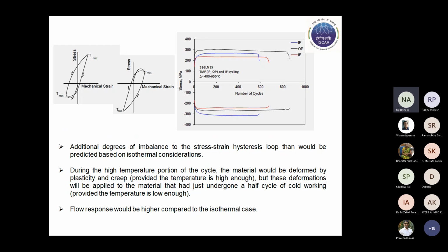So compared to the isothermal kind of cycling, here you can see an additional degree of imbalance on the stress-strain hysteresis loop compared to the situation under isothermal condition. Under isothermal condition, the tensile and compressive parts of the stress-strain hysteresis loop would be symmetrical, but in the case of TMF, there is an asymmetry in the tensile and compressive parts because of the differing temperatures during the tension and compression strain of the cycle.